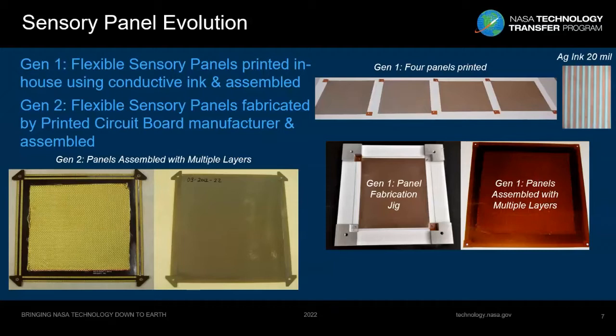The reason that it made it complicated is the first generation and the second generation, the sensory system was put together using a compression system that allowed the panels to be removed freely, and it required all of the individual traces to line up perfectly with contact pads on the rigid circuit board, and that was complicated when we were printing with the inkjet printer. We had some issues with some slight movement of the prints, so we actually went out and had these fabricated, and they turned out very nice. And you can see in the image on Gen 2, the one on the left is the front face, and they have Kevlar panels in between the 4 layers, Kevlar sheets, and the image on the right is the back side. Next slide, please.